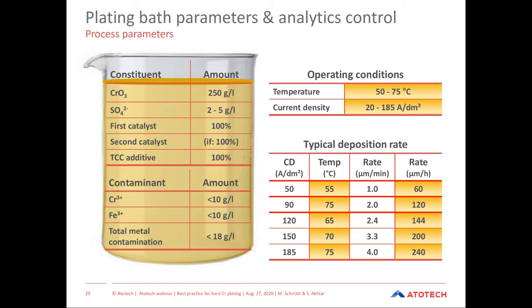The high-end 75 or 185 amps per square decimeter is then usually the high-speed plating in Dynachrome platers or for engine valves. Typically, the operation range of the HEEF process or of most of the processes is about 50 amps per square decimeter at 50 to 60 degrees centigrade, which will give you a plating rate of about 1 micron per minute, 60 microns per hour with the HEEF process.